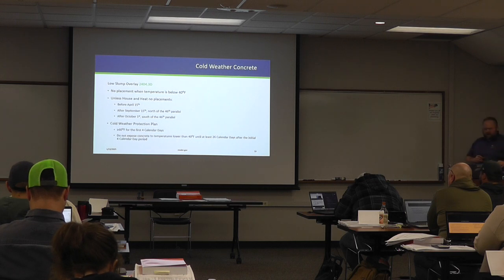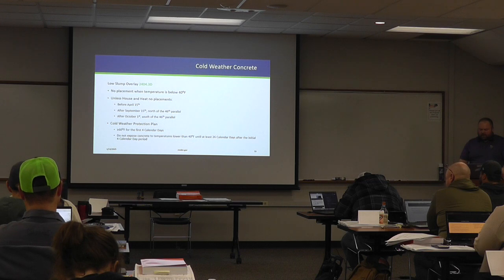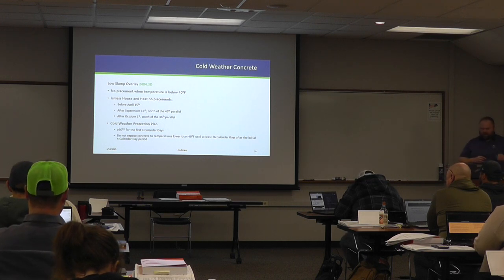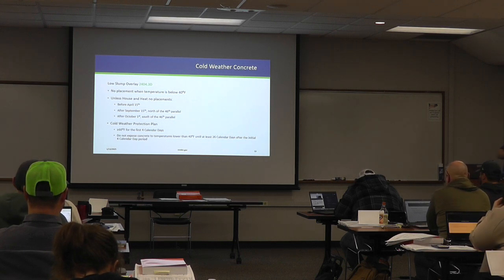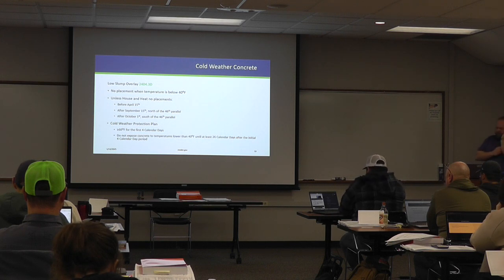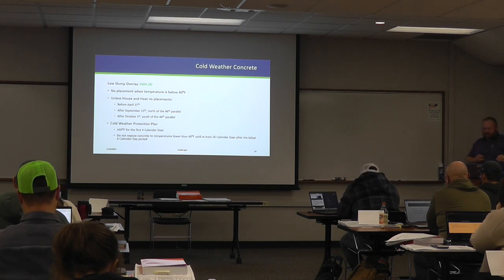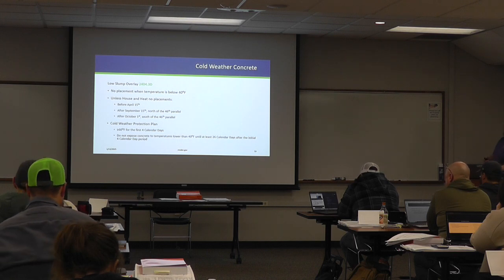For low slump overlays, we're not going to place when temperatures are below 40 degrees unless we house and heat. There's not any placements before April 15th, after September 15th north of the 46th parallel, or after October 1st south of the 46th parallel. And for a cold weather protection plan, we want to keep the concrete above 60 degrees for the first 4 calendar days and not expose the concrete to temperatures lower than 40 until at least 26 calendar days after the initial 4-day cure period.